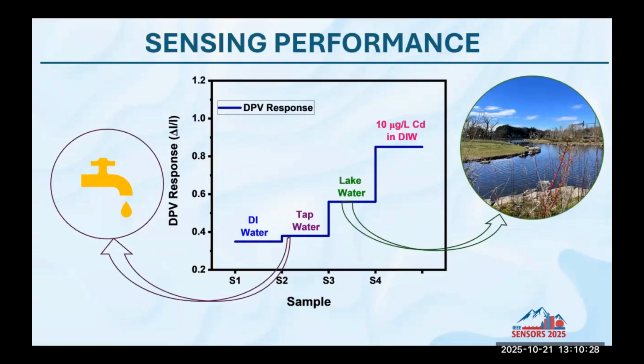And then when we tested with the lake water from the lake near our lab, we find the response has shifted a bit. But still, this response is quite low and almost less than half of the safe limit, which is 10 microgram per liter for cadmium.